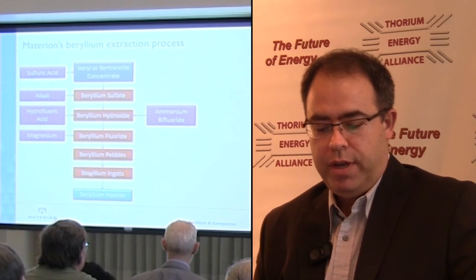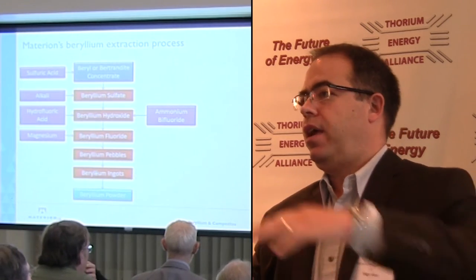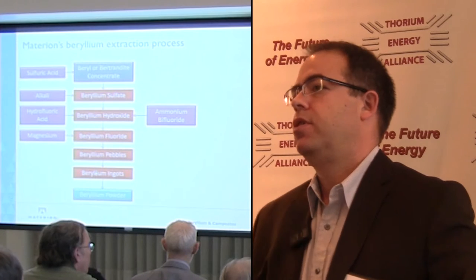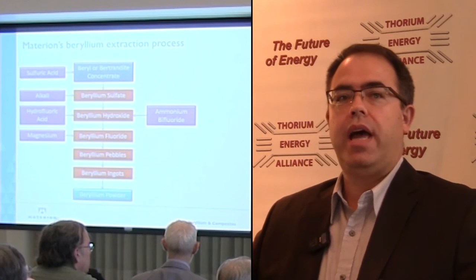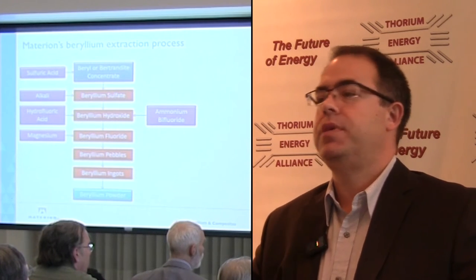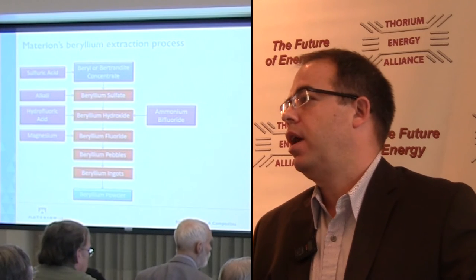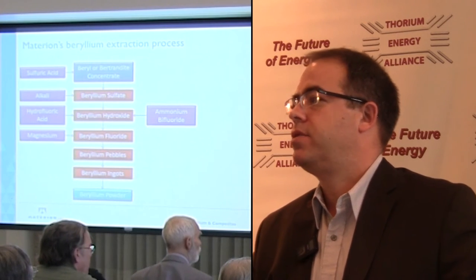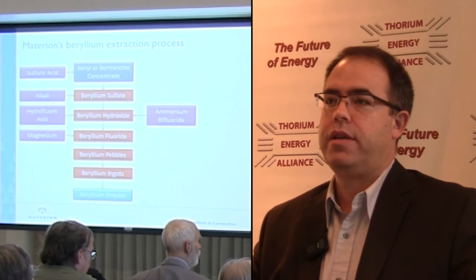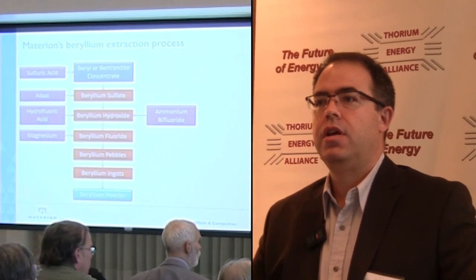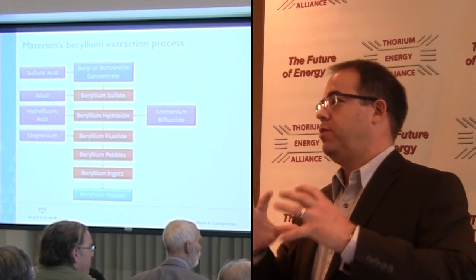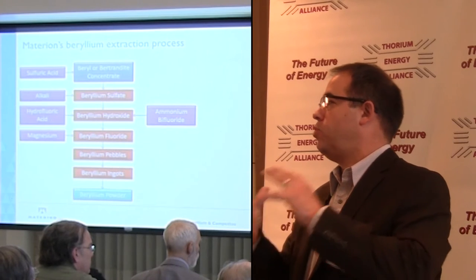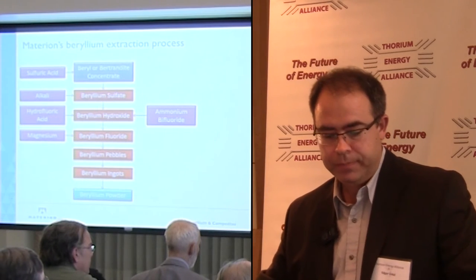Those pebbles, then we basically melt them. We make ingots, and the way Materion has done it forever is we actually grind the material down to a powder, and we do what's called hot isostatic pressing, cold isostatic pressing and sinter. So basically it's powder metallurgy. We make blocks, shapes with the final part.